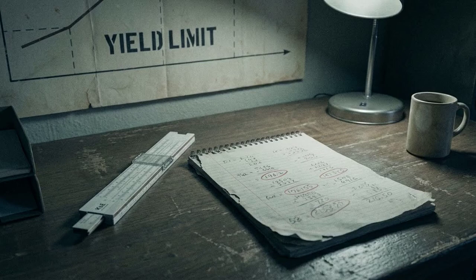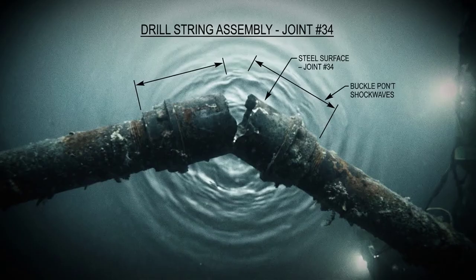The pipe sections are made of high-strength steel, but steel is not infinitely strong. At 4 million pounds of tension, the top joint is experiencing peak stress near 80,000 pounds per square inch, close to the material's yield limit. There is no margin for error, no reserve strength, no second pipe string waiting.